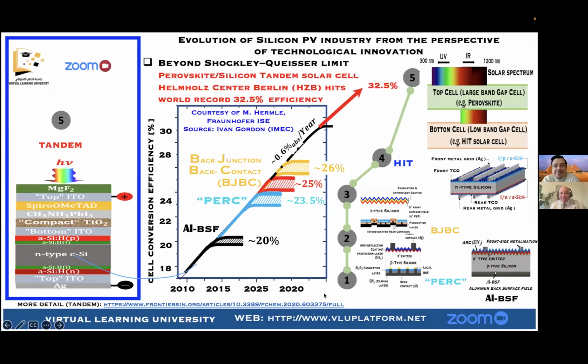You can see here, for example, the evolution of silicon technology. It starts from the aluminum back surface field. That's the first generation which you find in the market. Then the second generation, what we call PERC, with back surface field, where you can cut the back contact with laser. Then you go to another generation where the front contact is moved to the back contact, so the front is very free. And then there is the heterojunction solar cell with amorphous silicon and N-type silicon, and then the tandem.